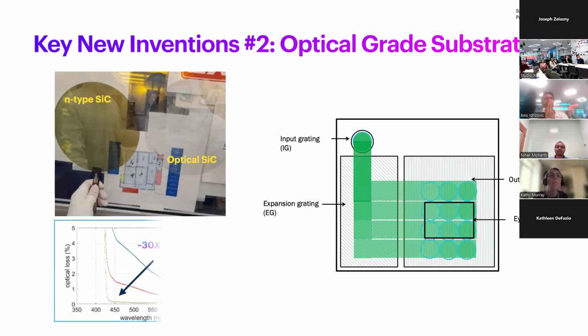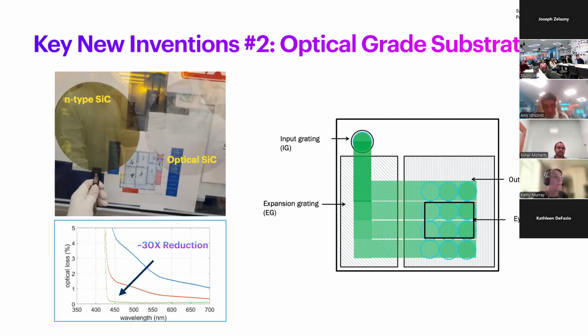Over the years, significant process and tool development in collaboration with our partners has enabled us to reduce the absorption by 30 times to almost negligible amounts for visible wavelengths. And you can see the results in an optical grade silicon carbide on the right here.